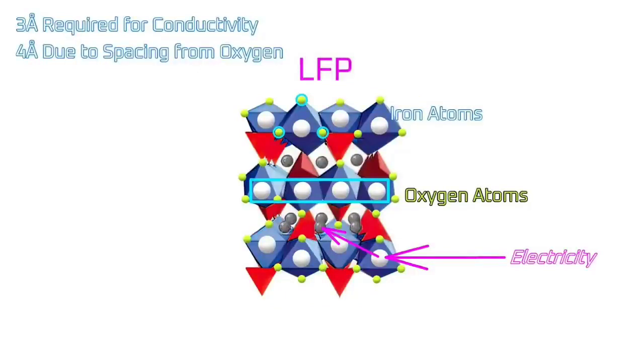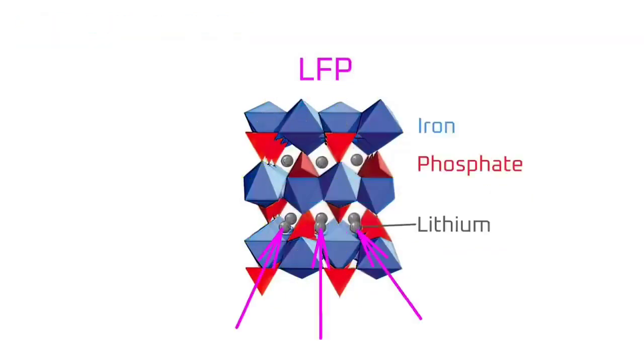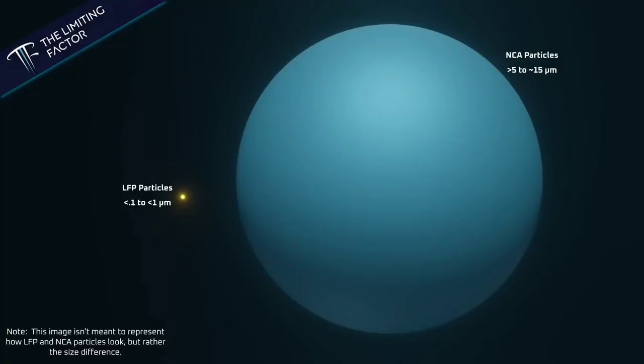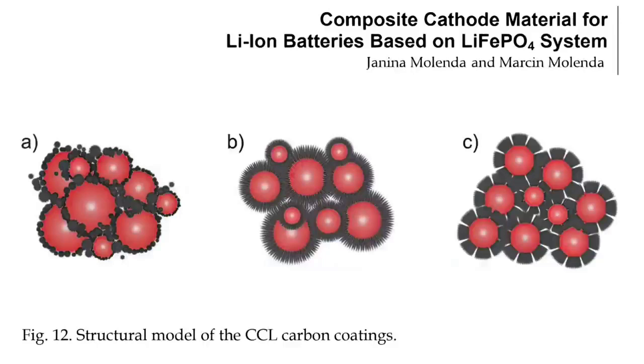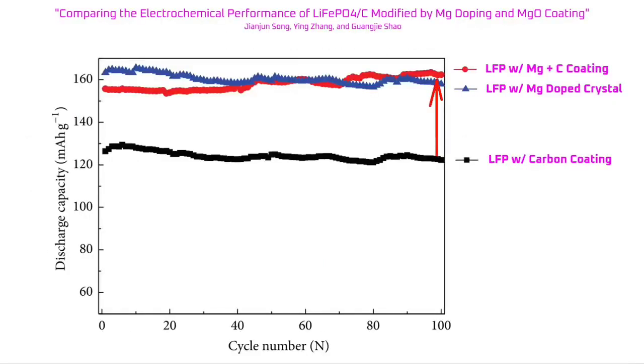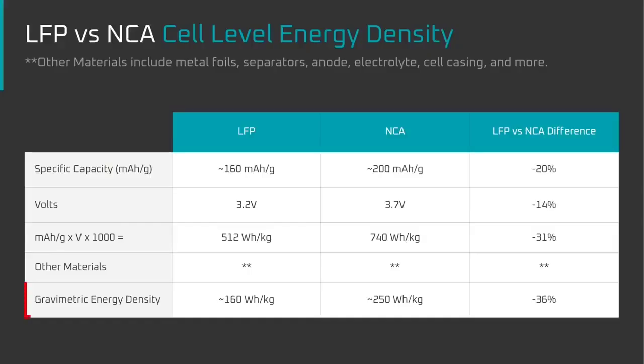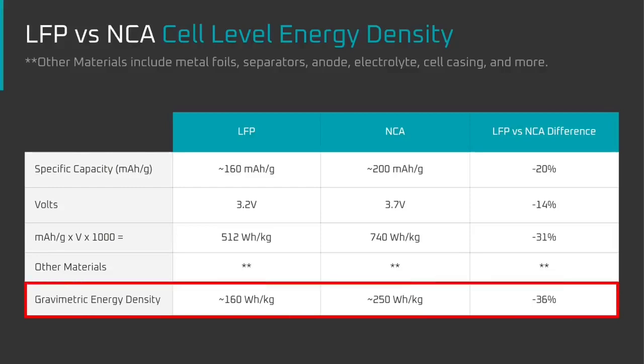Out of the box, LFP has issues with conductivity and moving ions in and out of the crystal structure. This was solved by making the LFP particles smaller, adding a carbon coating, and doping it up with elements like magnesium. Without those innovations, LFP wouldn't have been commercially viable. Even with those innovations, LFP is outperformed at the cell level by NCA. The gravimetric energy density of LFP is lower than NCA by about 36% for cells like CATL is using.